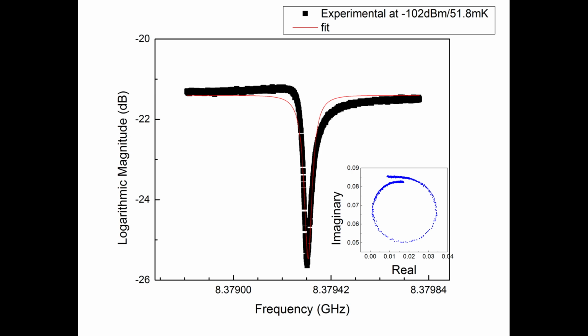Here you can see the Lorentzian fit in red, and then also the beginnings of the circle fit on the right. This is how we measure the quality factor, which is related to the full width half maximum and the frequency of resonance. The quality factor can be broken down into parts relating to the geometry of the CPW, as well as the materials used to construct a CPW, both of which are important to report in any type of experiment.